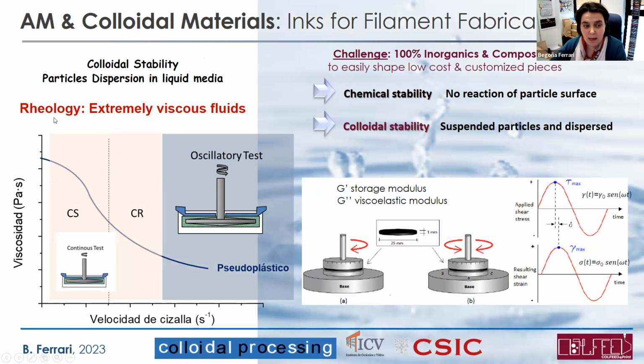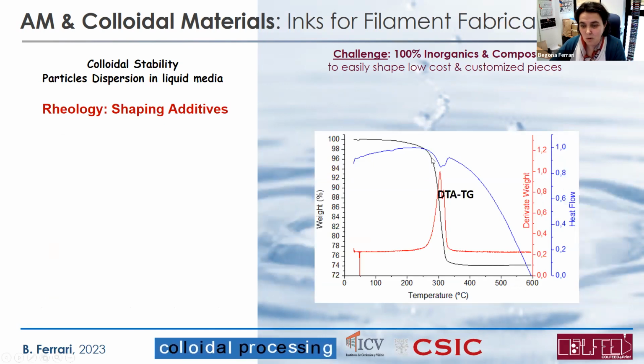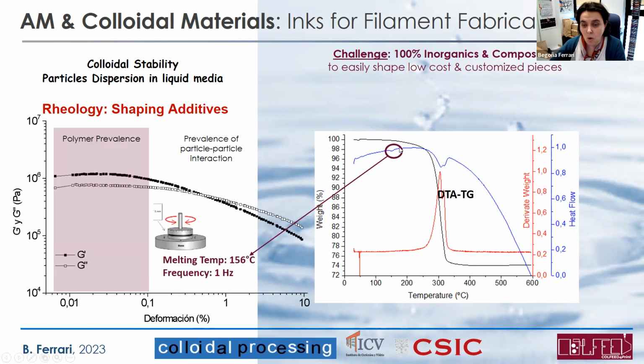and study the rheology of these thermoplastic composites using oscillatory tests, because we are talking about an extremely viscous fluid, like a thermoplastic composite melt. So we need to know more than the degradation temperature or the melting temperature. We also need to know how this thermoplastic behaves when you try to print it. This part of the rheology is very interesting to study, because it gives us an idea of how the matrix is working, and also how the particle interaction is effectively changing the fluidity of this melt.